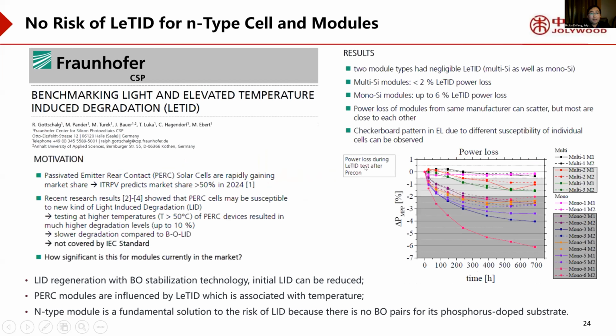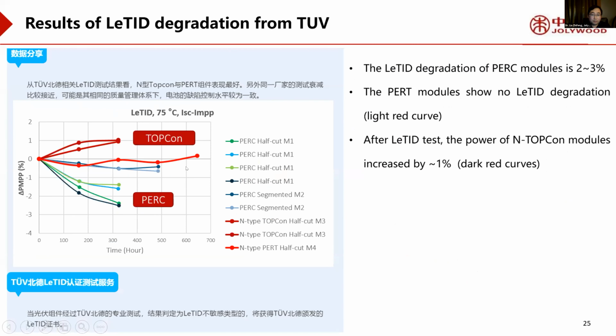3.9%. And next is about the LeTID. Firstly, we can find for the PERC, no matter multi or mono, we have a huge LeTID risk. And TUV Nord has also published some data about the LeTID test. They find that for the PERC modules, the LeTID is about 2 or 3%. For the N-type PERT modules, the LeTID is near 0. And for the N-type TOPCon modules, after the LeTID test, we can find the module power has some increase, about 1%.